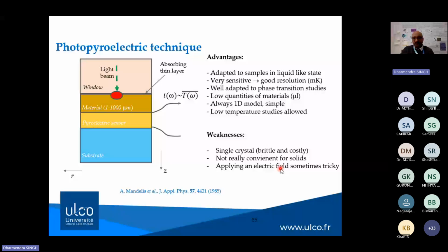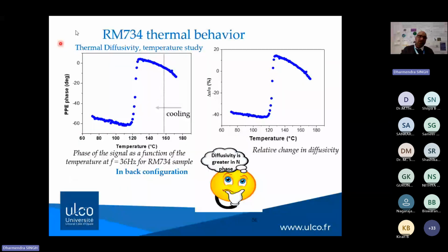With the RM734, we have measured the thermal behavior. You could see here the phase is nematic, and this is the ferroelectric nematic phase. You could see the signal strength is weak. So here we do a lot of mathematical treatment of the data, and we first estimate the thermal parameters called effusivity and diffusivity, and then we calculate the thermal conductivity.